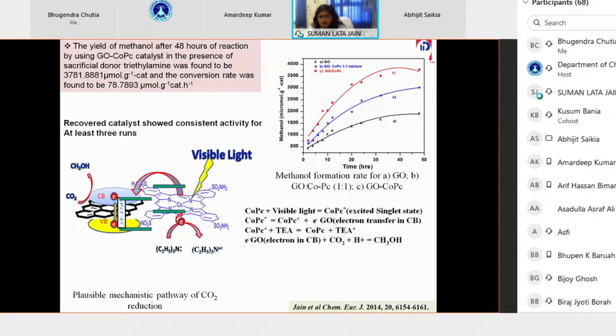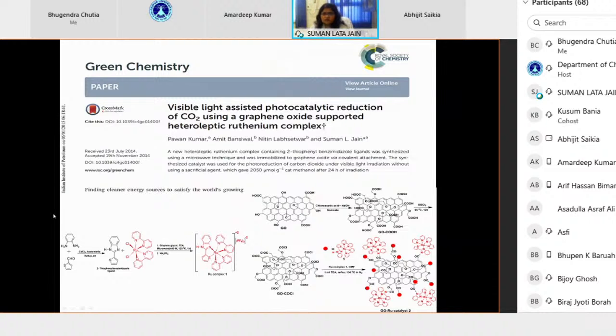Subsequently, we have developed a number of materials where we did not use any sacrificial electron donor. Our support itself provided the electrons, and the water which we are using in the reaction provided the necessary protons as well as the electrons for the reaction. So in other reports, we have not used sacrificial electron donors. Similarly, this is another work which we carried out in our lab. In the previous work, we used cobalt phthalocyanine. In this, we have used a ruthenium-based polypyridyl complex with some heteroleptic ligands. Two kinds of ligands we have used to design this complex.